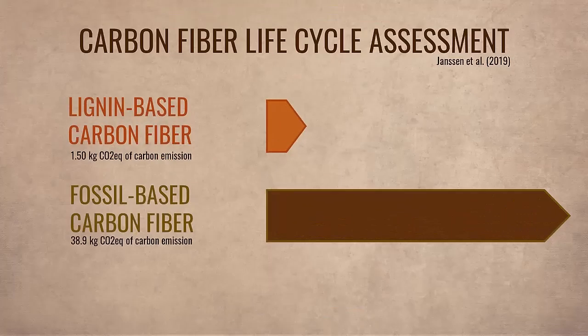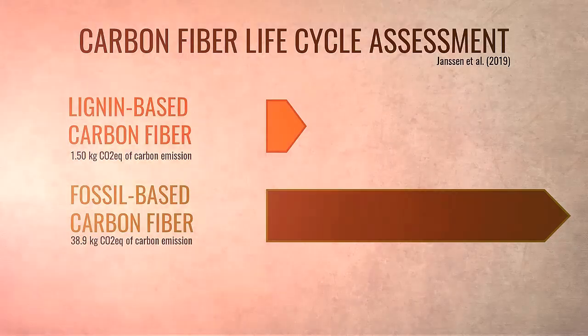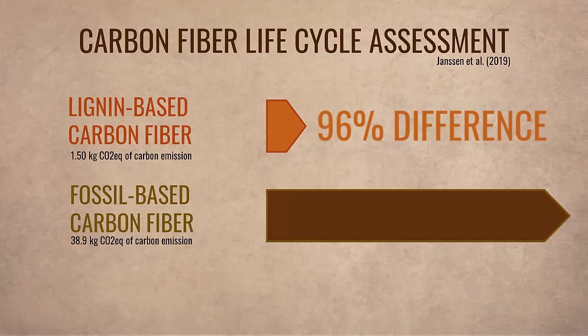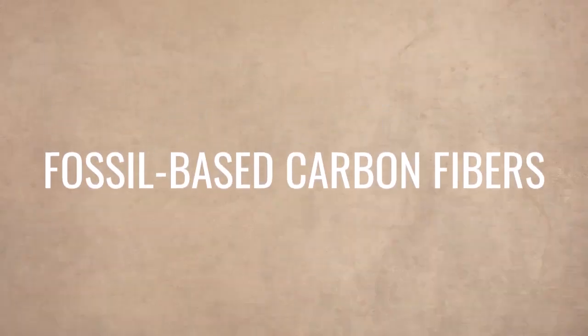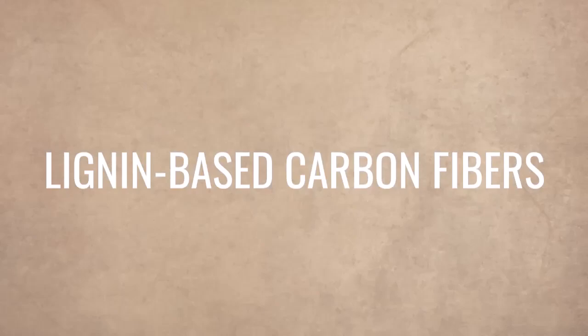Looking at the life cycle assessment of carbon fibers itself, Janssen et al. found that the climate impact from producing 1 kilogram of lignin-based carbon fiber is about 1.5 kilograms of carbon dioxide equivalent. On the other hand, 1 kilogram of fossil-based carbon fiber resulted in almost 39 kilograms of carbon dioxide equivalent. This is a difference of 96% in the resulting carbon emissions. So, from an environmental point of view, lignin-based carbon fibers have a huge advantage.